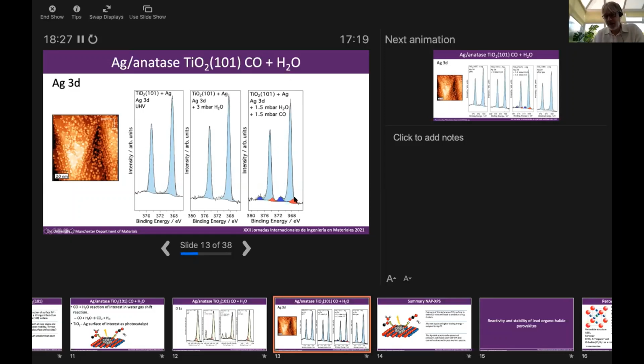So silver, like cobalt, is strange in that normally you expect that when you oxidize a species, you remove electrons from it, and the binding energy will increase. For example, as we saw with titanium going from 3+ to 4+, the 4+ is at a higher binding energy than the 3+ peak, because the 4+ has one fewer electron but the same nuclear charge, so it hangs on more tightly to those electrons. But silver and cobalt behave differently, and for reasons which still aren't fully understood, the binding energy of oxidized silver, so silver plus, is at a lower binding energy than silver metal.